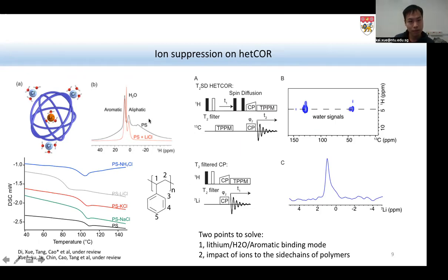The sample that I'm using here is different, it's not a protein sample, it's a polymer sample, polystyrene. What we observed is that for the polystyrene sample, the addition of different ions is able to change the glass transition temperature of this polymer, especially in the case of addition of lithium chloride. This change can be more than 20 degrees. So what makes it different from other ions? In a simple proton 1D, what we can see is that lithium chloride actually absorbs water and introduces a lot of extra water in the system.